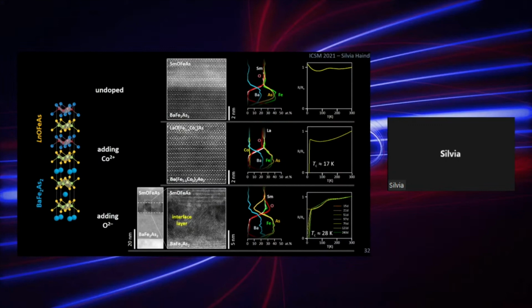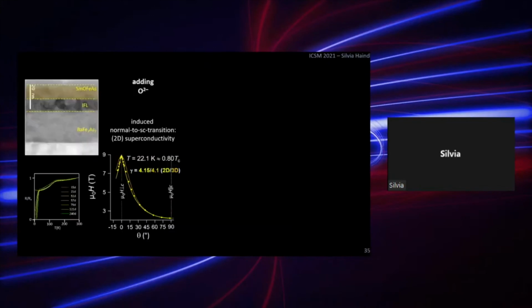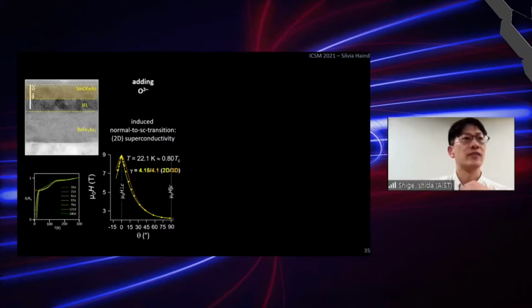But here we see signatures of a 2D superconductivity, and this means that the barium 122 layer is too thick to have a 2D signature, so we assume that the 2D signature appears in the upper samarium iron oxypnictide. Thank you very much. A very interesting result.